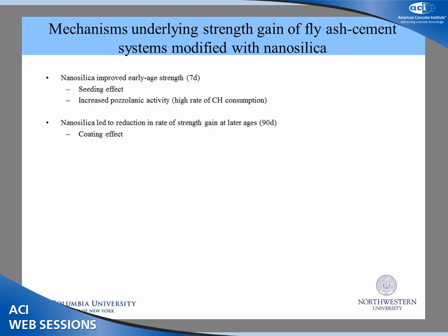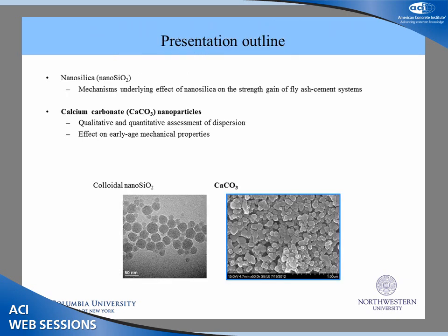So in summary, the mechanisms underlying the strength gain of the fly ash cement systems modified by nanosilica: they are improving early age strength gain through the seeding effect and also increased reactivity. But at later ages, due to coating, the rate of strength gain goes down. So that was a study on nanosilica. Now I'm going to talk about calcium carbonate nanoparticles.